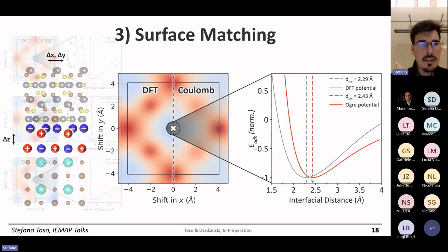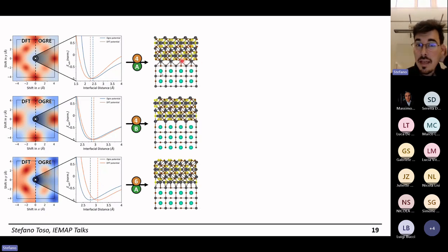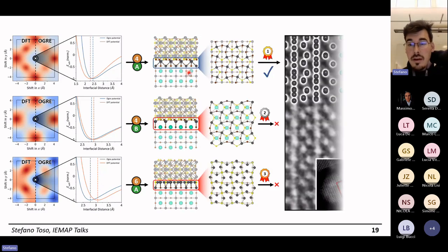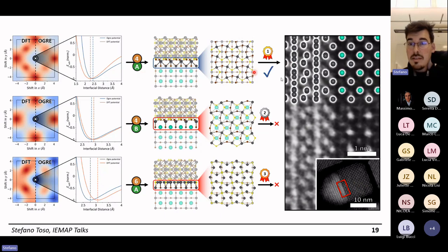When you use this potential, what do you get out? You get several evaluations for all possible interfaces, and, what we care about the most, an optimized structure for the interface. So here we have 3 possible candidates. They all connect very well, so they are reasonable. But we also get an energy ranking, because now we know, for example, that this interface, energy-wise, is better than the other 2. And when you check the experiment, so you take the particle, put it under an electron microscope and check what's going on at the interface, you find out that our prediction is accurate. The experimental structure is exactly the predicted option, and it also has the predicted geometry, which is quite an achievement.